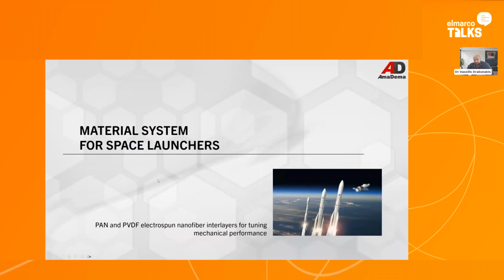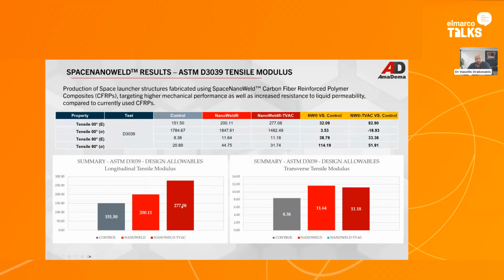Now, let's see specifically another component, a carbon fiber component, that is in collaboration with Airbus Defence and Space and is designed for applications in space launcher structures. Here you can see that the control compared to the NanoWeld, and the NanoWeld after processing within TVAC examination, has a significant increase in the tensile modulus as well as in the transverse tensile modulus. This increase is quite significant and includes also the deviation. So especially here, we can see an increase up to 33%, which is quite significant for aerospace applications.